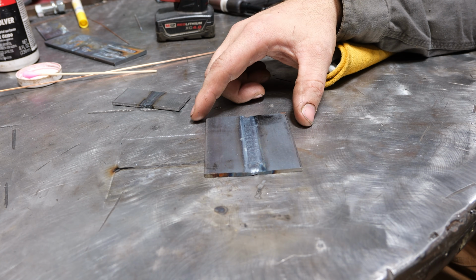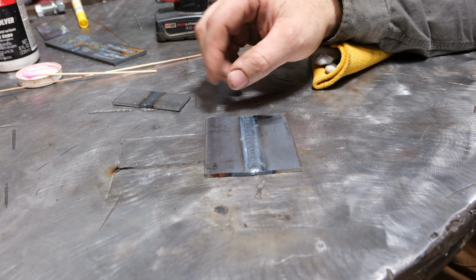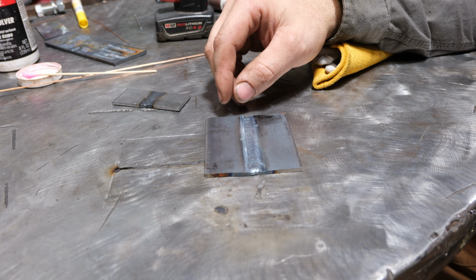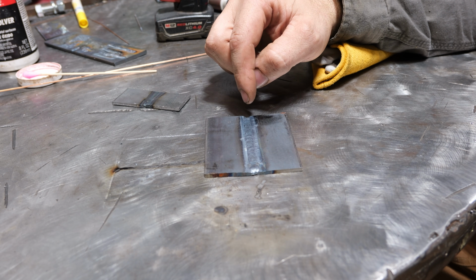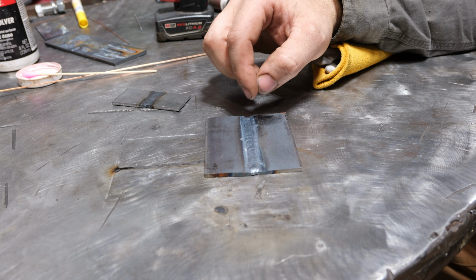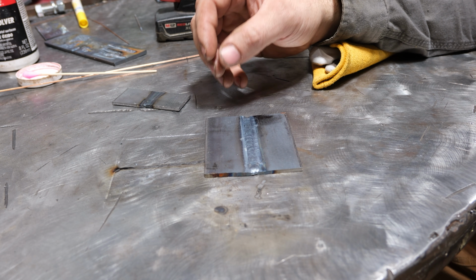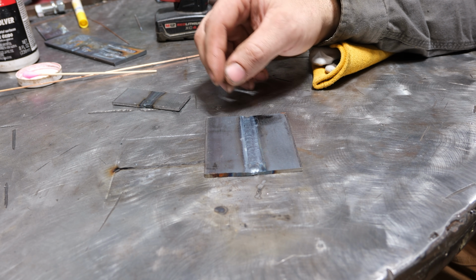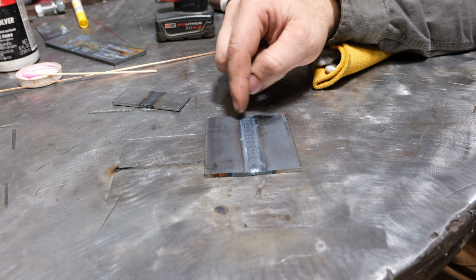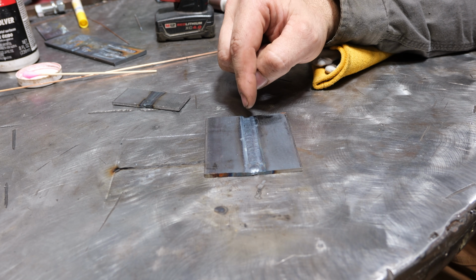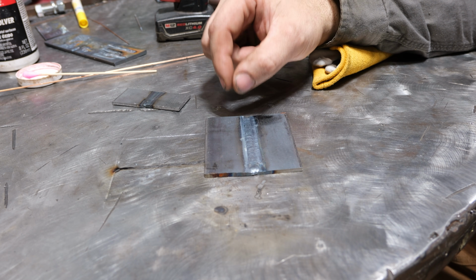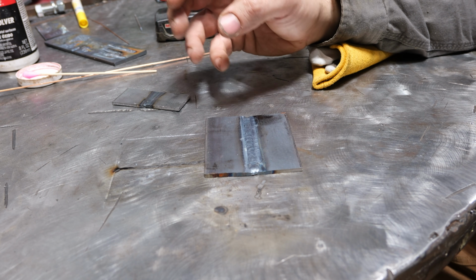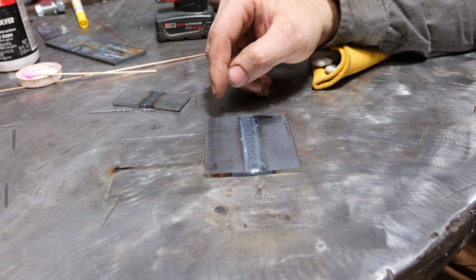So on this set of plates, I left a gap of about 1.6 millimeters or about 1/16 of an inch, and then added filler to help bridge the gap. When you have a gap like that, it is not possible to do a fusion weld simply because you're just going to melt the edges of both plates and they're not going to melt together. The gap is simply too much, but by adding filler, you're able to bridge the gap.